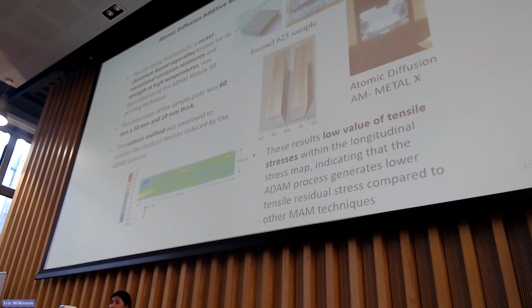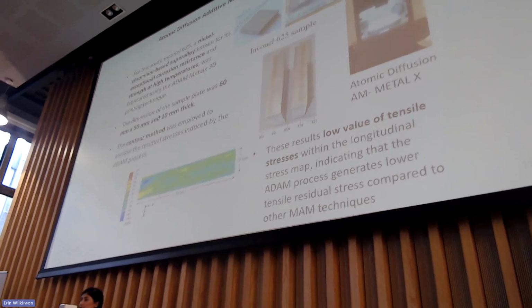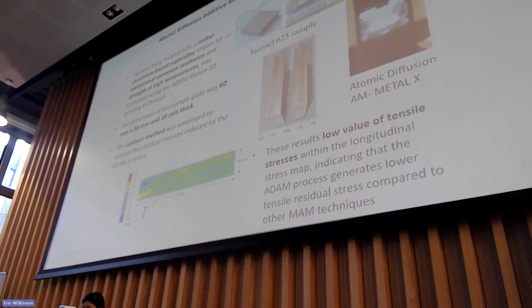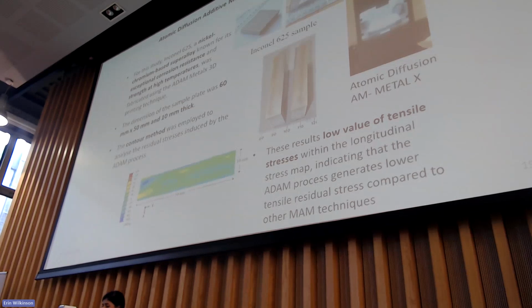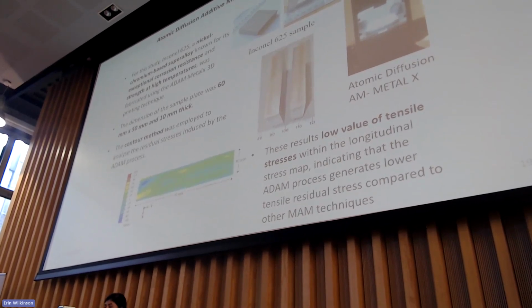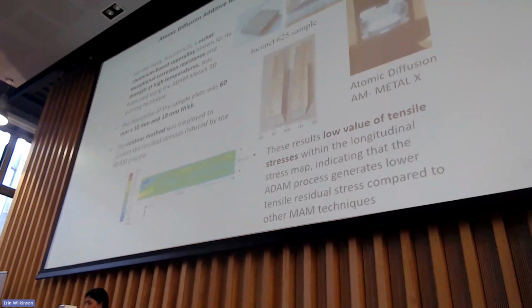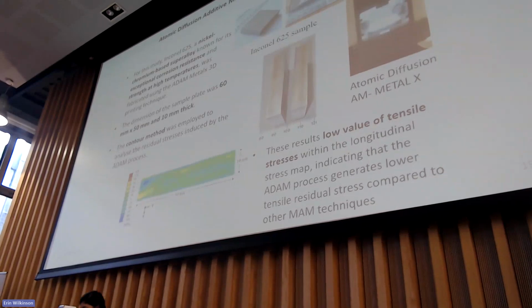So what we did, we tested the sample for residual stresses. As we all know, residual stresses are not good for the metal. They can cause a premature failure during service. So it is very good to find out whether this type of process can produce any adverse effect within the sample or not. So we did this study for that. We created a sample using 625. We tested it with a destructive technique, which is the contour method. And we used the contour method for these samples. Here you can see some results.